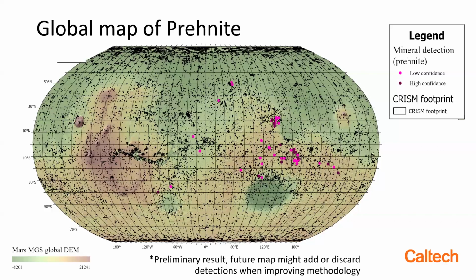This is our initial global map. It's a preliminary result, and we are presenting the center IDs or center locations of the different CRISM images where we think there might be prehnite on Mars. In purple, you see the ones with high confidence of prehnite detections, and in orange or pink, the ones with a lower confidence. This can be because it has a combination of features, so we're not sure if it's a mixture with other minerals or if we are detecting another mineral. What you can see is that most detections are clustered around Nili Fossae and in Terra Tyrrhena. Next slide, please.